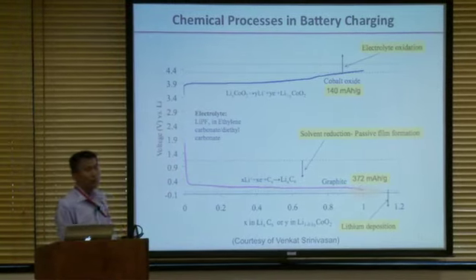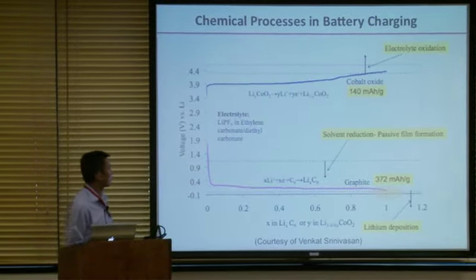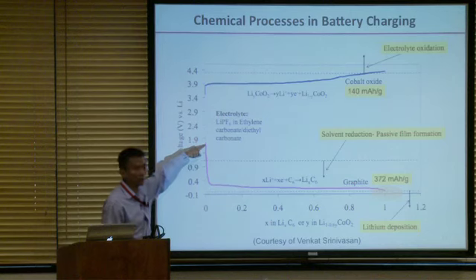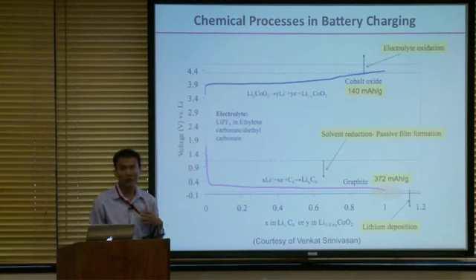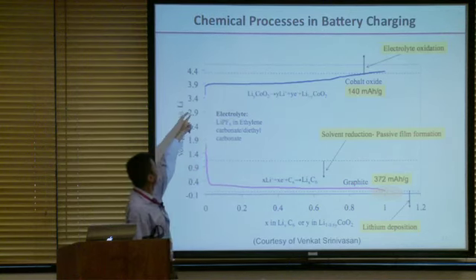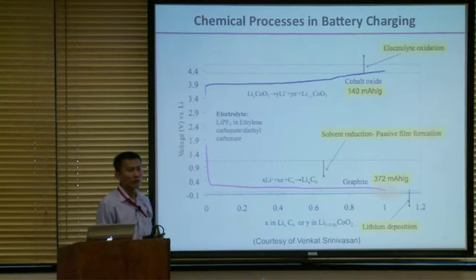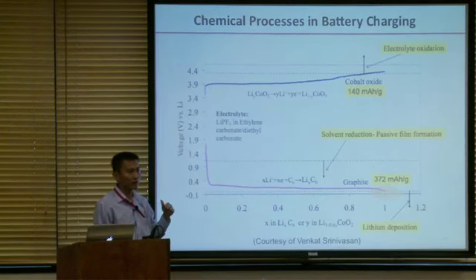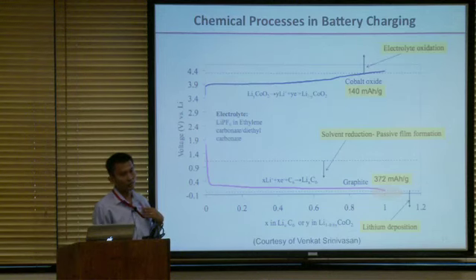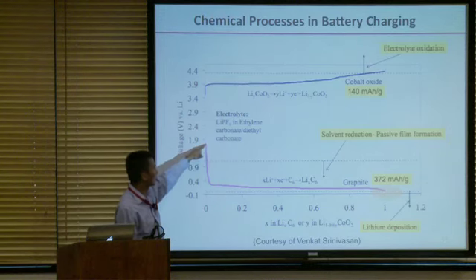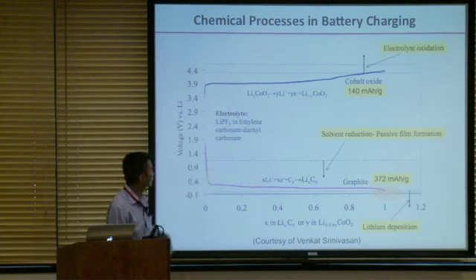So during the charging process, let's look at what will happen. You have a battery, you measure the carbon potential versus a reference, that's your lithium metal. You also measure the lithium cobalt oxide. Now you start to put in current, you monitor the voltage to see what happens. Let's look at the negative electrode first, that's a carbon.